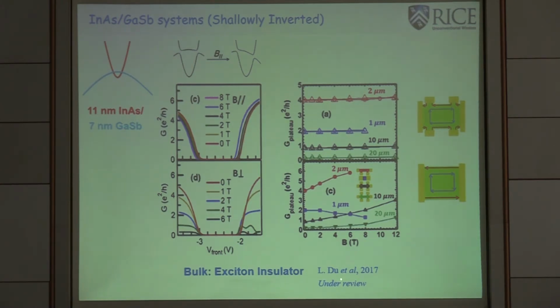And then later we do measure the optical absorption in this region, and you can find the signature of the exciton formation, and also you can find the predicted energy gap related to the exciton condensate. So even though this can be treated as a single-particle picture of the hybridization-induced gap, and you can understand this by looking into the band structure, in reality, at such a low density, there might be strong influence from electron-hole interactions or even exciton insulators. Now, if we apply a magnetic field, what happens for the edge state? And then we can measure those in different types of samples.